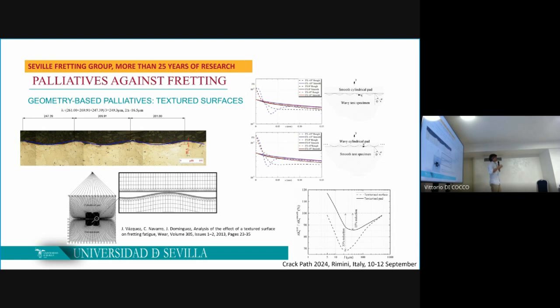Here we can see similar result that I have shown before with the surface removed due to shot peening. We can observe here the fatigue parameter along a line again starting from the hot spot. You can observe that very close to the surface, the values are higher than compared with the smooth cases. But also we can observe that below the surface, a substantial decrease of the value is produced. So a good behavior is expected with this kind of waviness. Also, we analyze the mode 1 stress intensity factor in that case. It's important to know that when you introduce the waviness in the test specimen, always the mode 1 stress intensity factor is lower than that obtained with the smooth case.